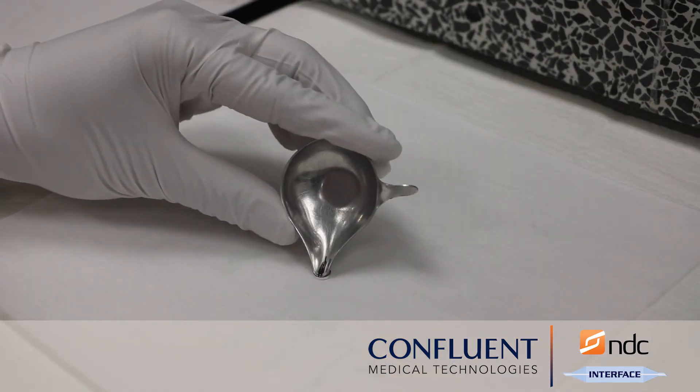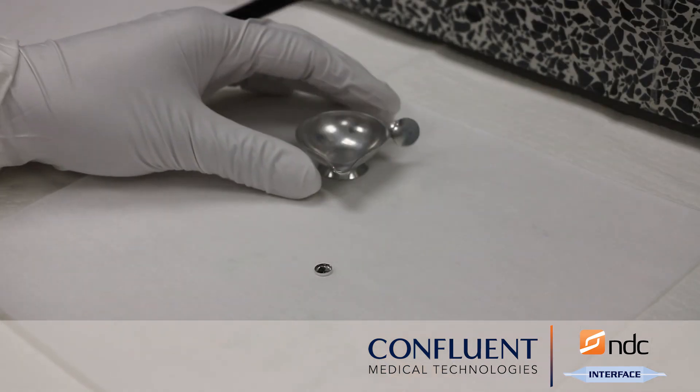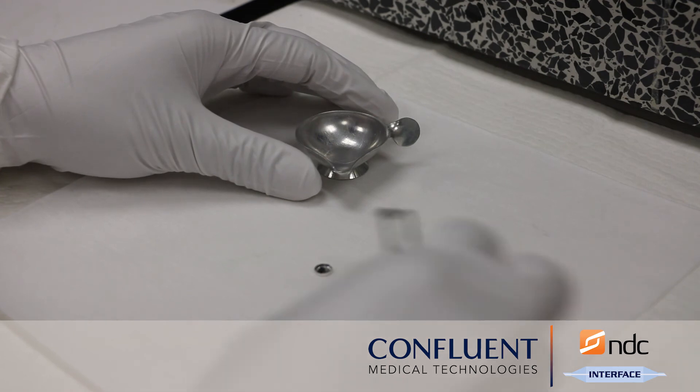So unlike a traditional bend and free recovery test, DSC is purely thermal in nature, and there's no strain that's put on the sample during the test. So there can be an offset between the two techniques because of that.